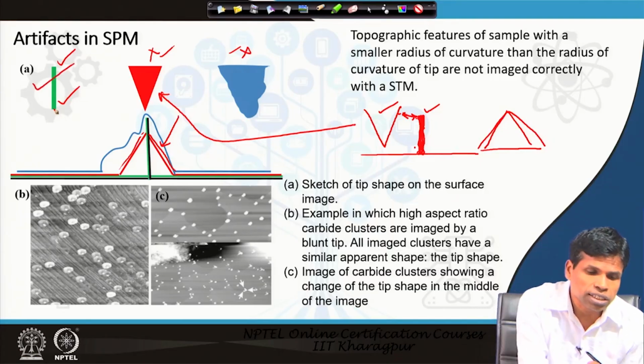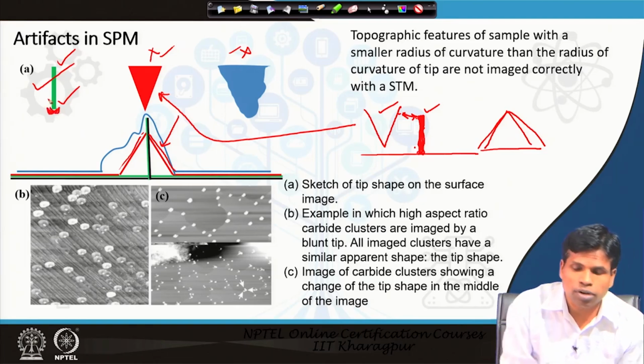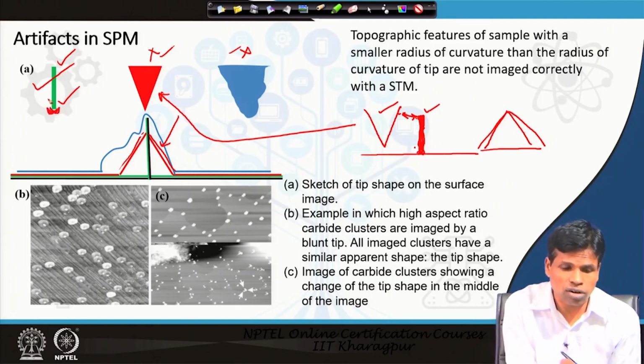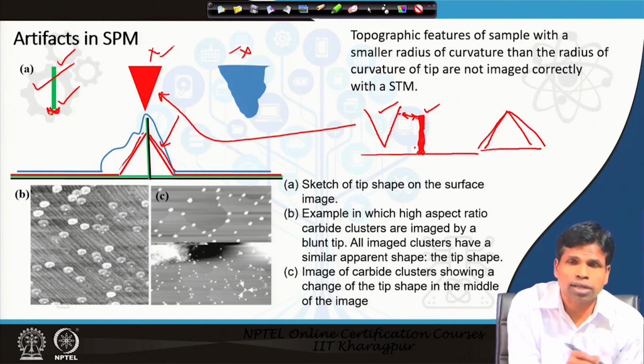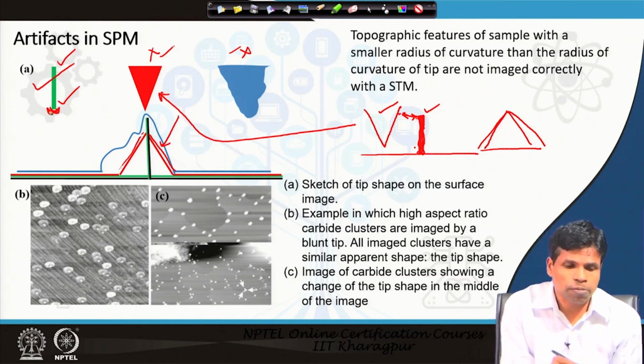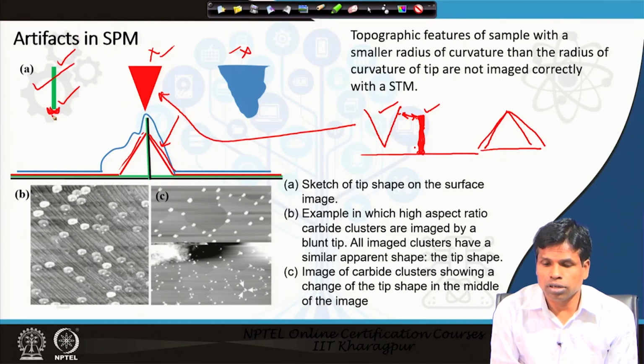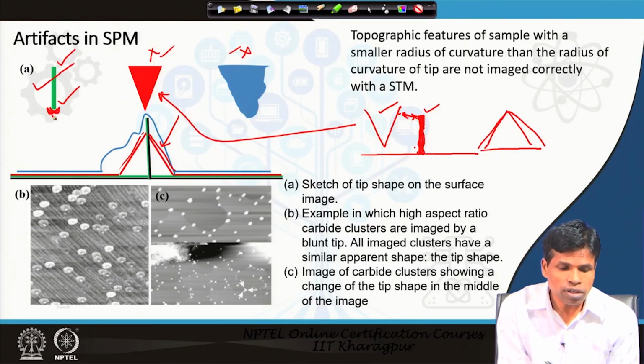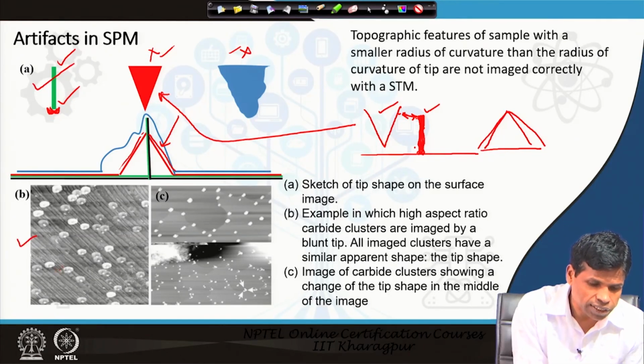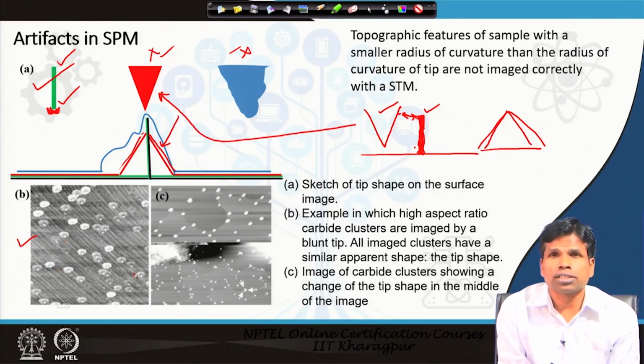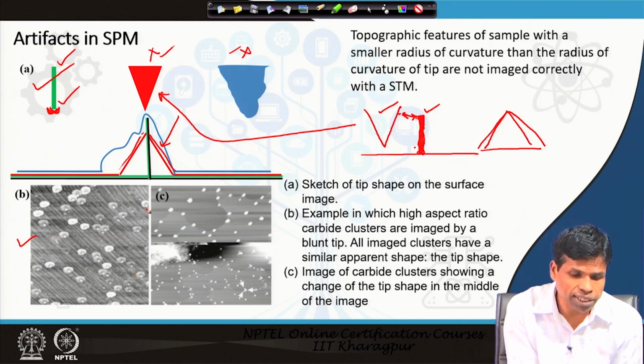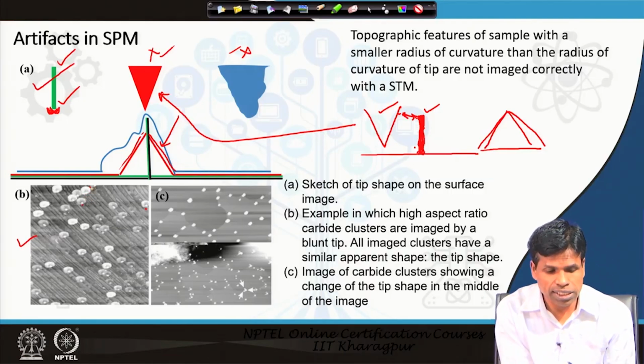In addition to that, the tip curvature should be smaller than the curvature of the sample. If the tip curvature is larger, then we cannot get the correct image of the sample. As you see in these cases, almost all features are looking similar, but in the middle there is a brighter feature, and around that there is a halo, and these are carbide clusters.